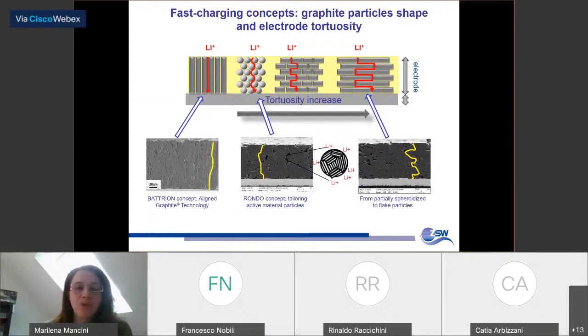From a geometrical point of view, here you can see that there are different expected tortuosities of the electrodes depending on the orientation and on the morphology of the graphite particles. What we have investigated in a project called Rondo is how the particle morphology affects the anode kinetics. From a geometrical point of view, it is clear that spherical particles lead to lower tortuosity than particles which are more flat.